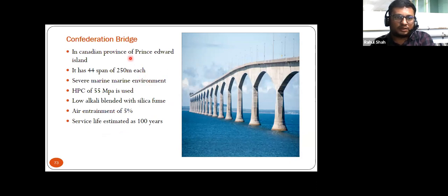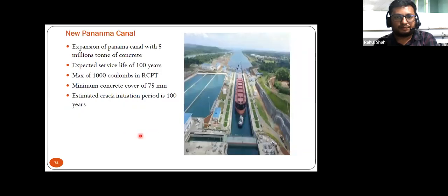this bridge, Confederation Bridge, in Canada, in Prince Edward Island. It has 44 spans of 250 meters each. It has severe marine exposure conditions. High performance concrete of 55 MPa is used. They have used low alkali cement blended with silica fume. Air entrainment is 5%, and they have estimated a 100 years service life.